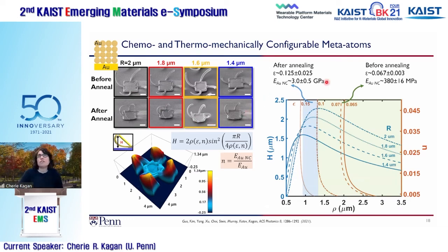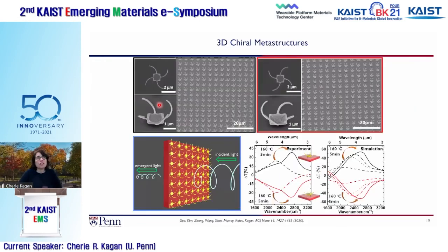I won't go through the details of the model in the interest of time, but you can see that we can get the same kind of 6.5% strain by this ligand exchange. And then when we anneal it, we can even double that strain and really get the structures to bend even further, as you can see here in the examples before and after annealing. But what could you do with this? Maybe I'll focus now on examples of thinking about the two enantiomers and making chiral materials.